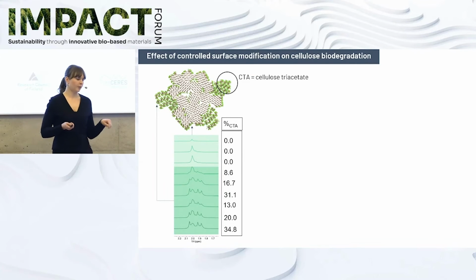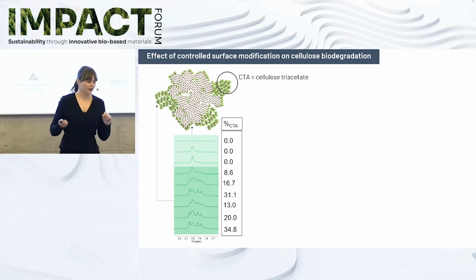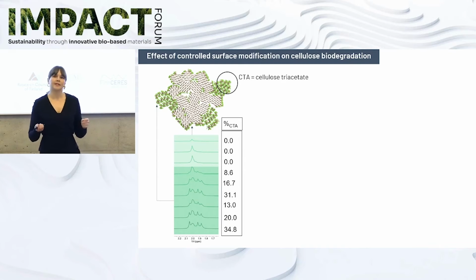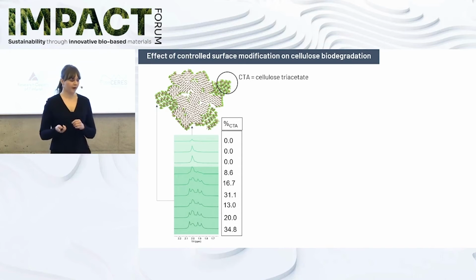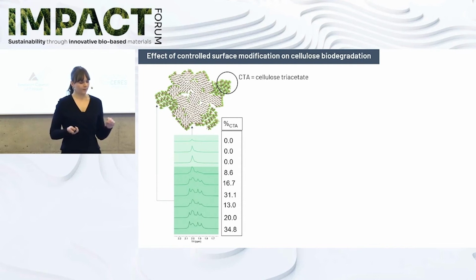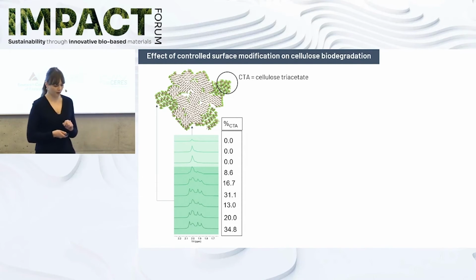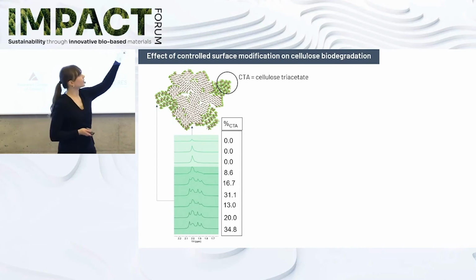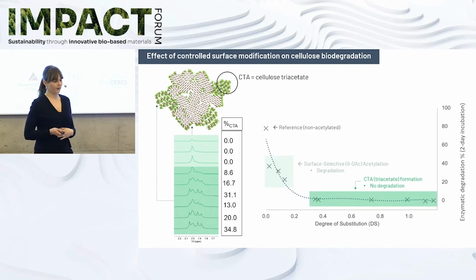And here is the same NMR data for the 9 different test points. From the same peaks, we can also calculate the percentage of cellulose triacetate forming on the surface. And cellulose triacetate is similar to commercial cellulose acetate, so it's very resistant to biodegradation because all of the hydroxyl groups are modified there. And we see that with these three upper experimental test points, there is no cellulose triacetate formation. So the reaction is really occurring only on the surface of the fibrils.